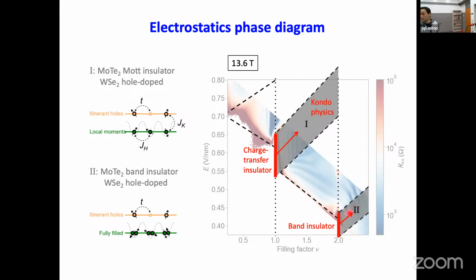We just dope a band insulator, but not doping in the MoTe layer, but doping in the tungsten layer in that case. Okay, so these two correspond to two different scenarios. One is with your Kondo lattice physics. The other is actually just a doped band insulator. You should not expect any Kondo lattice physics in the system.